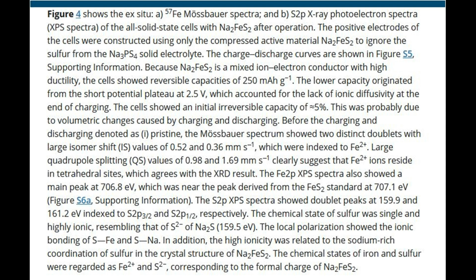The lower capacity originated from the short potential plateau at 2.5 V, which accounted for the lack of ionic diffusivity at the end of charging. The cells showed an initial irreversible capacity of 5%. This was probably due to volumetric changes caused by charging and discharging.